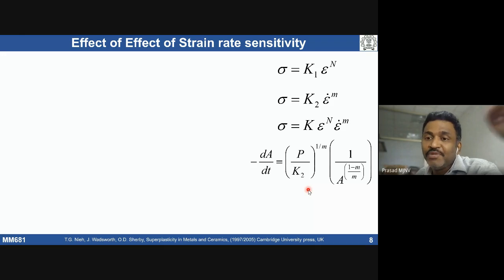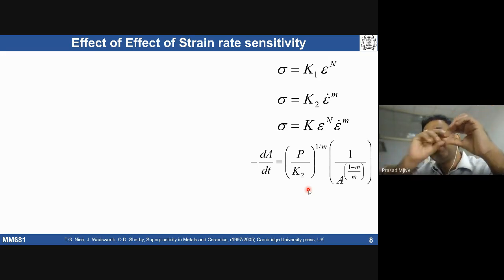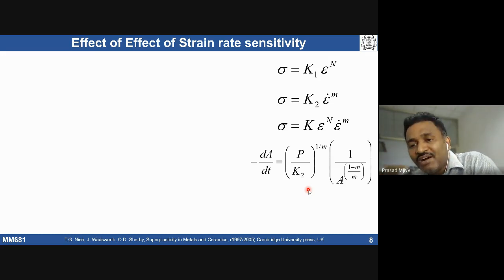Because m is equal to 1, above the glass transition temperature, if you deform a glass, if you pull the glass, it can flow like anything. If you take a thick rod, we can make a very thin wire, a glass fiber, out of it because m is equal to 1. They're actually independent of area. The rate of change is a constant.